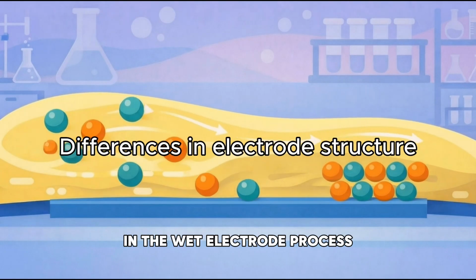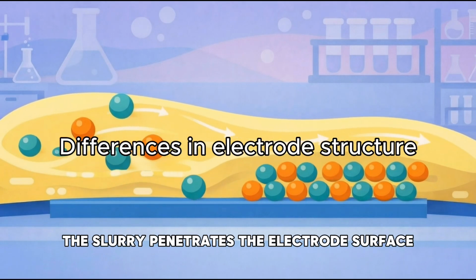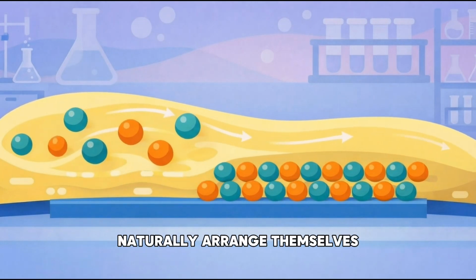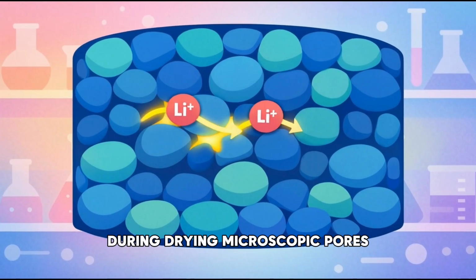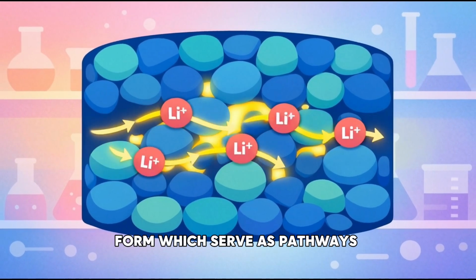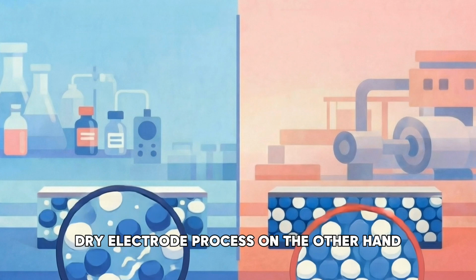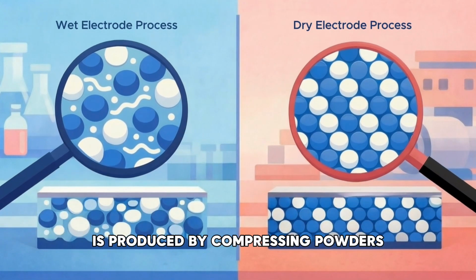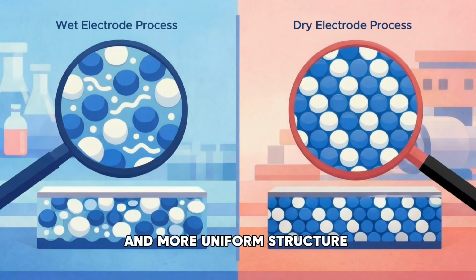In the wet electrode process, the slurry penetrates the electrode surface, allowing particles to naturally arrange themselves. During drying, microscopic pores form, which serve as pathways for lithium-ion transport. Dry electrode process, on the other hand, is produced by compressing powders, resulting in a denser and more uniform structure.